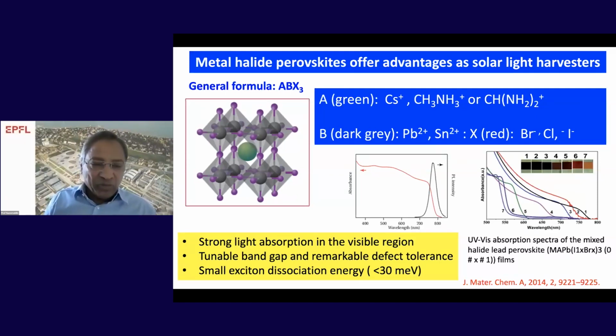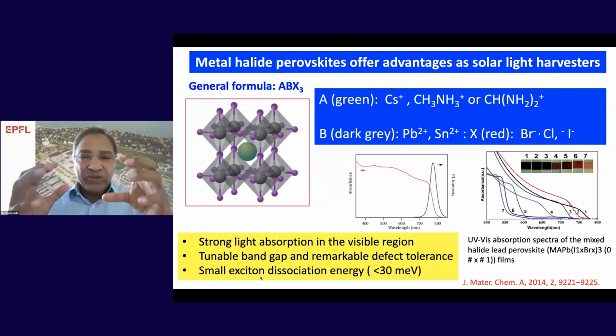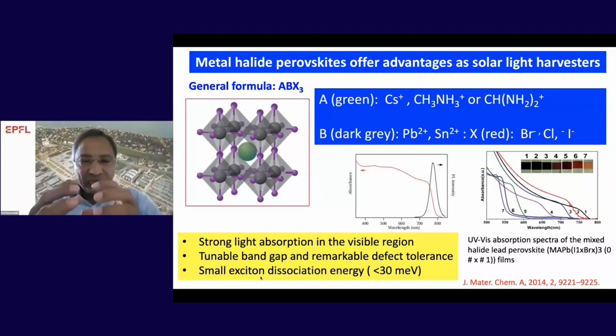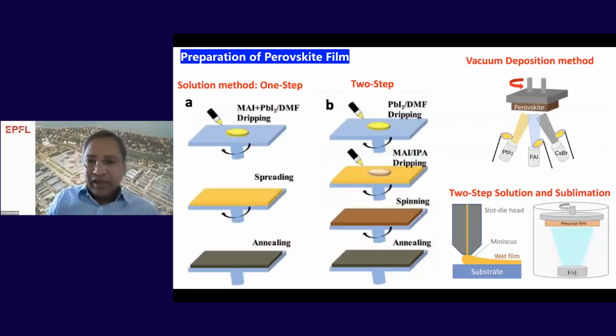The third important property of this material is a small exciton dissociation energy. So what does it mean? So when you shine light on the perovskite absorber material, you create positive and negative charges. They are separated instantaneously. So this dissociation energy is typically less than 30 millielectron volts. So these are the very interesting properties of this particular material. So how do you deposit this material to make the solar cells?